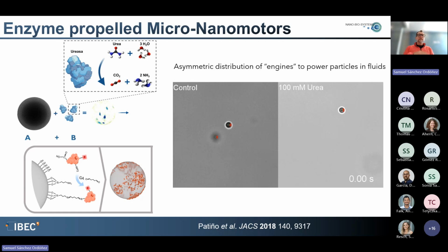So what we do is we decorate the nanoparticles around with enzymes, which take up the substrate, which is in the solution, and generate the chemical gradient that moves the particle forward, as you can see here. So passive particles, traditional particles that we normally do, are not moving. They only have Brownian motion, but if these particles have urease enzyme, for instance, this is one example. We have many, and this is under a patent that is now in territories, like the decoration with different enzymes to generate motion, right?